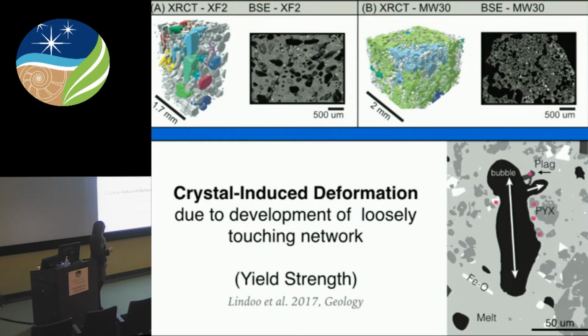And I think what's happening, and best illustrated by this figure down here, is that the crystals are causing the bubbles to deform. And essentially, as the bubbles are expanding, the crystals, some of which I've highlighted in pink, are sort of acting as guardrails as the bubbles expand. And so, as you can see, this bubble ends up kind of expanding vertically through this part of the sample, and then expanding a little bit more uniformly where there's no crystals.